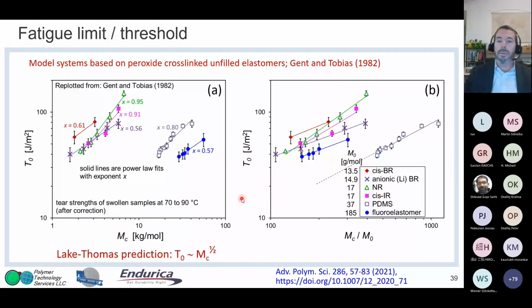So other elastomer types were shown by Gent and Tobias. So they also brought in polydimethylsiloxane, which is the main building block of silicone rubber, and a fluoroelastomer. And they plotted things as a function of crosslink density or molecular weight between crosslinks. So as you go this direction, you're getting more crosslinks, higher crosslink density. And what they showed was, compared to the crosslink density prediction of Lake and Thomas, about a factor of a half, they fitted these and they varied, but they were in the right direction. They were positive slopes, and some of them were quite near to a half. And so that was generally shown to be in agreement.